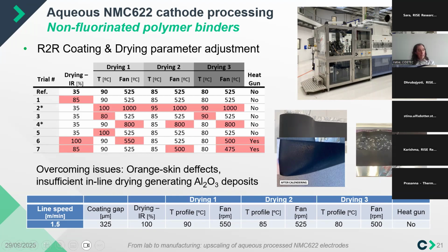Even when you think that at the end of the line the electrode is dry, as we are seeing here, we have found that you can find aluminum oxide deposits on the bound electrodes, particularly when this supposedly dry coated layer is in contact with bare aluminum. The drying was continuing over time, even when packed or stored into a dry room. There was still water being dried out of the layer and reacting with the aluminum, creating this passivation and these aluminum oxide deposits, which is not nice.